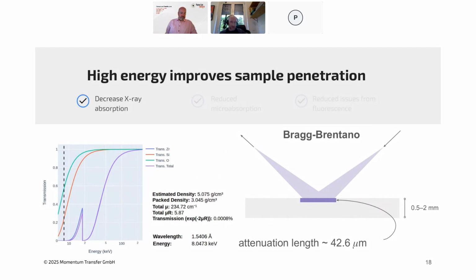so absorption goes down. So in this case, we have mu, which is the linear attenuation coefficient of the sample, which is 234 inverse centimeters. And if we use copper K alpha radiation, which is the typical radiation for most lab systems, which is an energy of about 8 keV, then the attenuation length of this zirconium silicate sample is about 42.6 microns. So that's a very thin bit of material that is all you need to essentially stop all of the X-rays